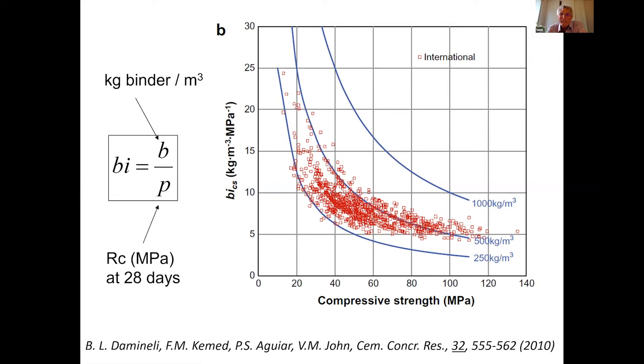A very interesting correlation, which was published a few years ago by the Brazilian team, is this type of plot in which they ask the question, how many kilograms of cement or binder do I need to get 1 megapascal of compressive strength? And what you see is that the evolution of the plot, with something like 500 data points, as far as I remember, shows that it gets narrower as you go to high performance concrete. In other words, it tells you there are many different ways to do bad concrete and not many ways to do excellent concrete.